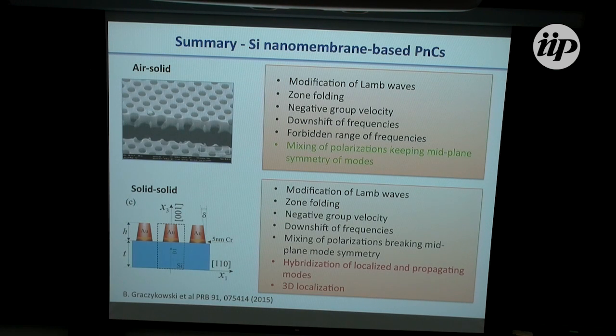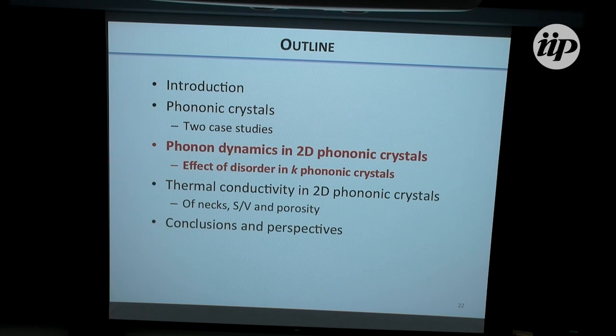So to summarize, these phononic crystals exhibit modification of Lamb waves, zone folding, negative group velocities, downshift of frequencies. There is a range of forbidden frequencies, or a phononic gap. In the case of the holey crystals, or air solids, we also have mixing of polarizations, but they keep the mid-plane symmetry of the mode. In the case of the solids, we have a hybridization of localized modes and propagating modes, plus the 3D localization. Okay, so that's the story on the characterization of phononic crystals.